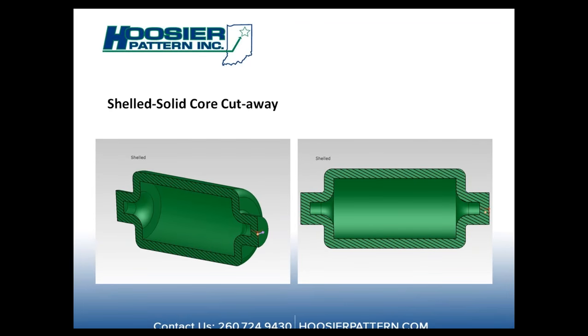Now the hybrid cores are cores that are shell, but inside there is unbound raw sand captivated inside. This is a nice thing in that you can't have metal migration into the core, causing some problems. We've all had that one on a casting. It can also help eliminate some issues with core clean out. Because it's loose sand, as soon as the core starts breaking down, all that sand just pours out of the casting in clean out, instead of, if it was solid, you might have to get in there and work on it.